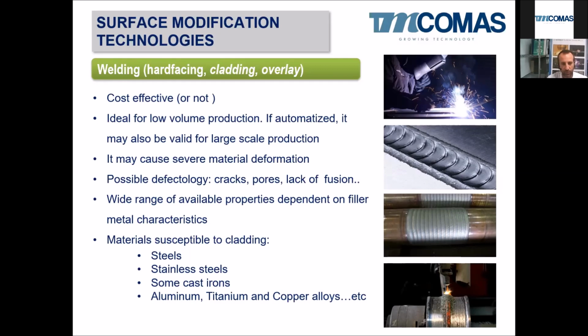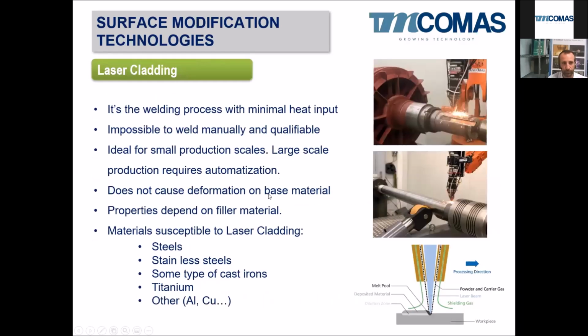Materials susceptible to clad or to weld or to protect by welding: steels, stainless steels, some cast irons, aluminum, titanium, copper alloys. Here it's very important in welding, the weldability. We have to take precautions when the base material is not weldable or it's difficult to weld, because there may be a lot of defects, cracks, pores, or bad experience. So the weldability of the base material is a critical point to apply welding.